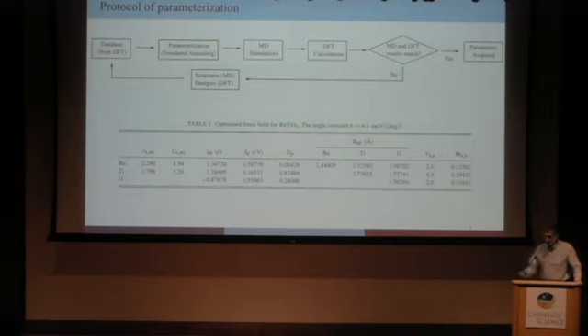Okay, so one of our recent successes is getting this bond valence model to work for barium titanate. It's a prototypical ferroelectric material, but it has all the phase transitions from rhombohedral to orthorhombic to tetragonal to cubic, and so it was fairly difficult to do. And so there was some simulated annealing in which you take parameters and do molecular dynamic simulations and then check with density functional theory whether the energies and the forces agree well, and if they don't, then you can use additional structures to refit until you're happy with the parameters.